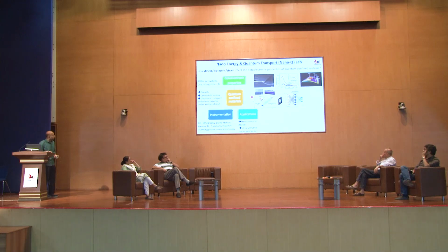This one is again the application part, neuromorphic. So we tune the defect, basically through defect engineering. We introduced defects in MoS2 and we found that their memristive property increased significantly compared to the pristine sample. Again, another example of defect engineering.